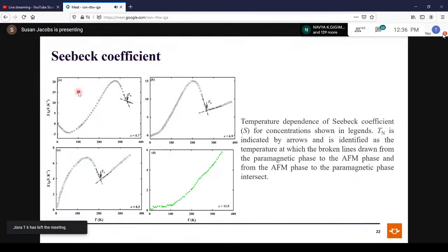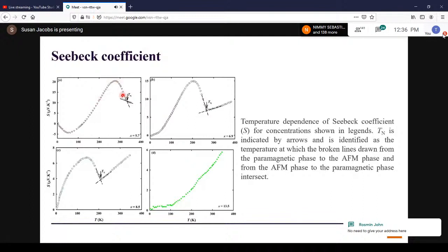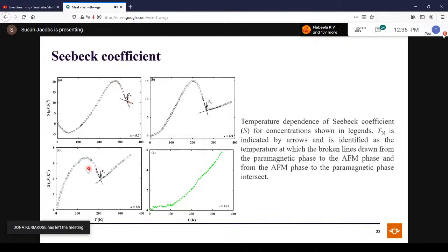Next physical property is Seebeck coefficient, or thermal transport measurement, from which we extract the Seebeck coefficient. Now you can see here the anomalies are enhanced compared to electrical resistivity measurements. So you have a dome associated with the transition temperature, and this dome is suppressed and shifted to lower temperatures as you increase the vanadium concentration.